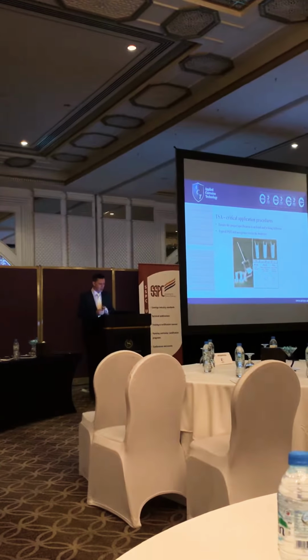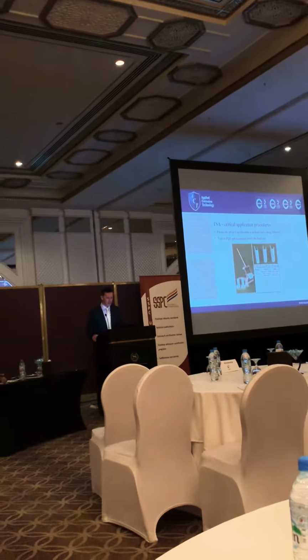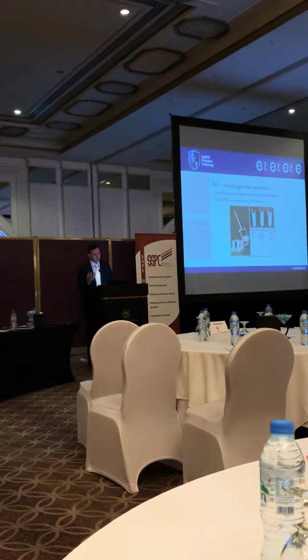The QA checking for TSA is a little bit different to other types of project, and there's an interesting picture there of the bend test that's done. So the plate is sprayed with the TSA and then put through the machine and bent, and then there is a pass-fail criteria in the SSPC standard to ensure that the adhesion of the material onto the substrate is there accurately.